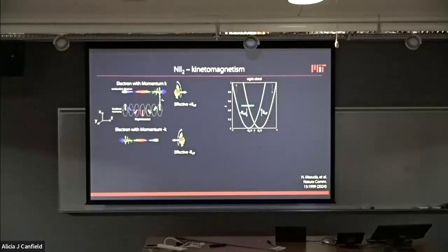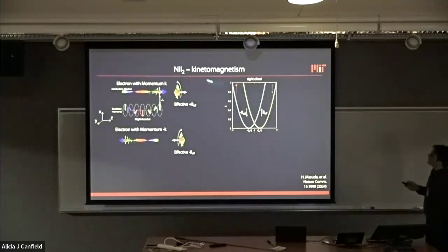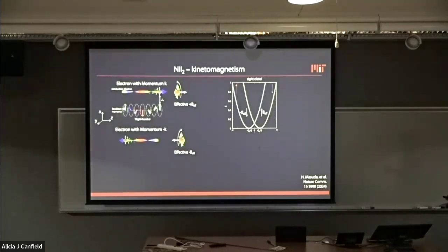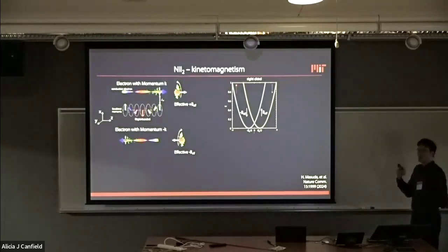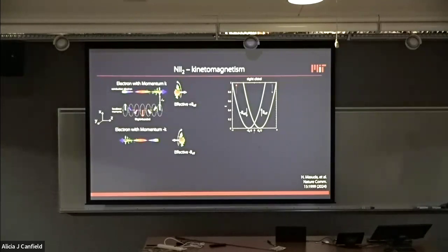So the very last part is about the chirality and switching of chirality. Nickel iodide is an example of kinetomagnetism. So the idea here is that when you have a spin spiral, or in this case a spin helix, that has a certain handedness, if you have an electron that moves with momentum in a certain direction, say positive direction, plus k, it will feel an effective magnetic field that's coming from the spin texture. This is very similar in a way to the chirality-induced spin selectivity. Very similar type of effect, but it doesn't come from the chirality in the lattice structure, it comes from the chirality in the spin structure. And an electron with opposite momentum feels an effective magnetic field which is opposite.